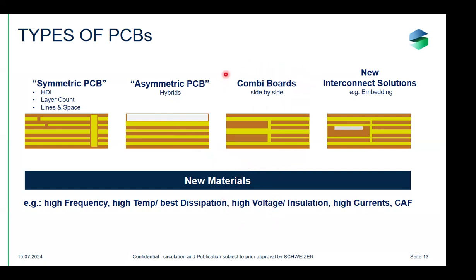We then developed so-called Combi boards. If you look at the schematic cross-section, you see that you have heavy copper on one side and standard copper on the other side. You might have a 4-layer construction in this area of the board, and a 6-layer construction in another area of this board. And this is something which was not possible in the past.